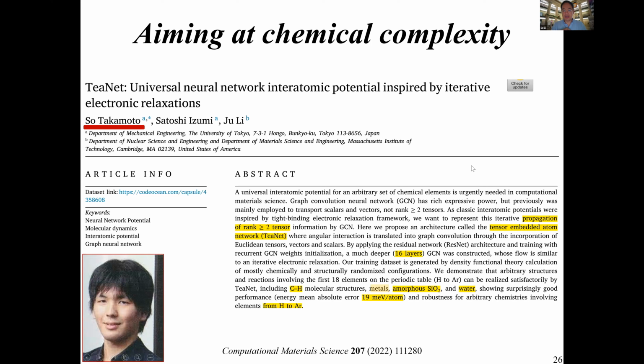And so we set out to develop this called the Tensor Embedded Atom Network. And we end up with half the chemical accuracy, which is about 20 meV per atom, for the first 18 elements on the periodic table from hydrogen to argon. And one unique thing about this is how we train the model. We do not bring any a priori chemical intuition into the fitting. We really randomly throw all these elements together in the simulation box. So no pre-existing crystals, because we just don't want to bias the neural network.